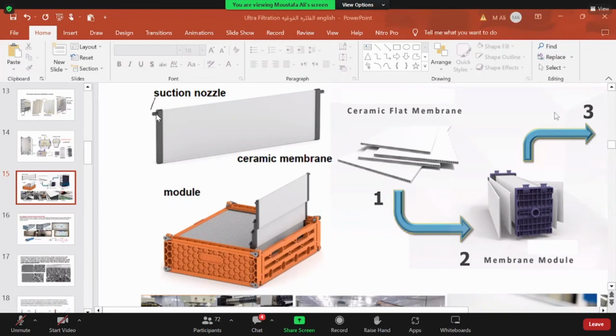The number of nozzles, from both sides or one side, depends on the flux rate of the membrane. So we can control the diameter of this to be sufficient for the flow across the membrane surface. The other option is to have this block, also polyphenylene oxide or Noryl part, with grooves to fit into these plates directly, and the water or the filtrate is gathered not through these two nozzles, but through one main outlet connecting the complete set of plates.